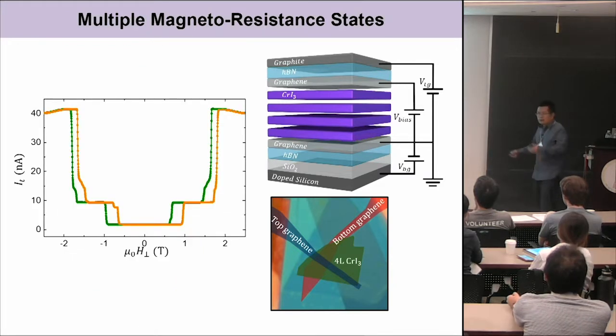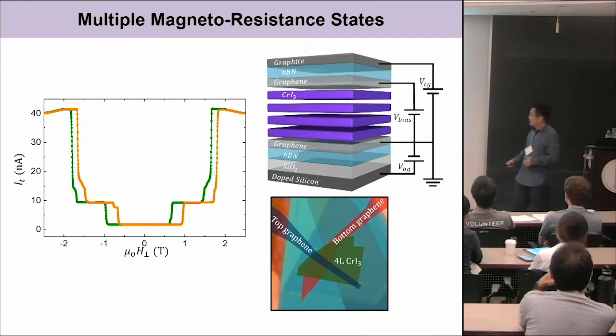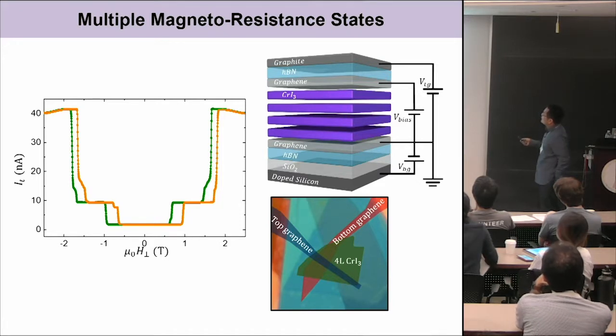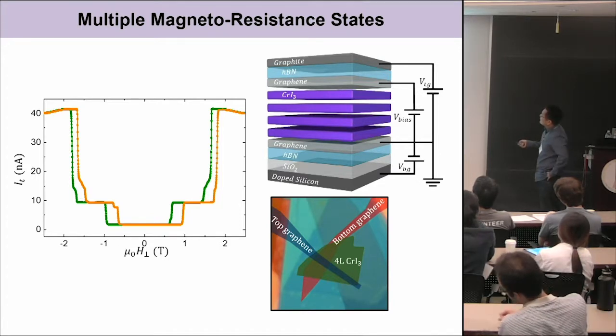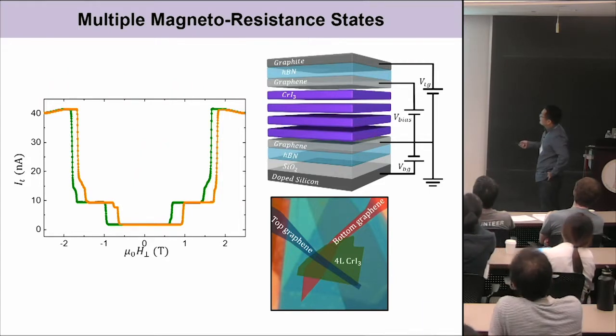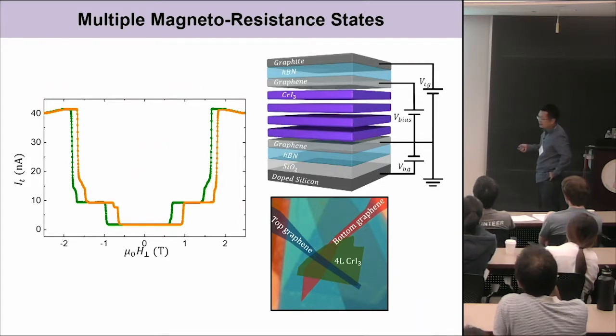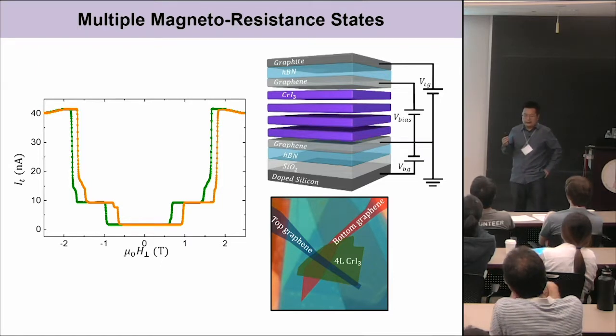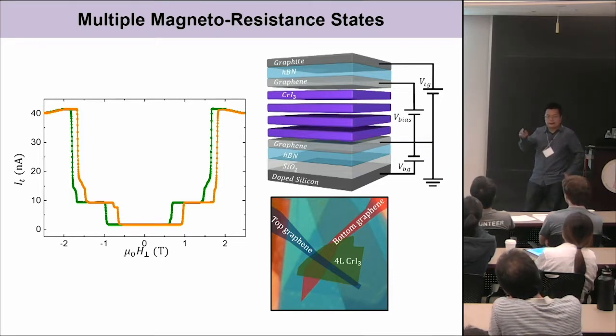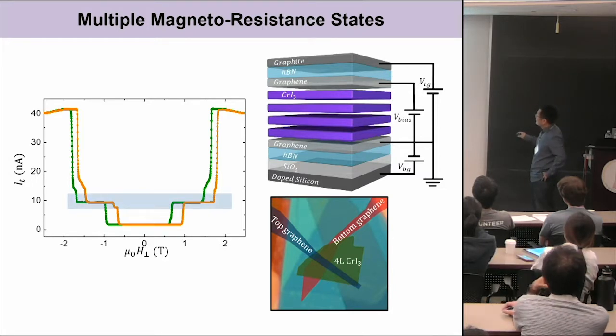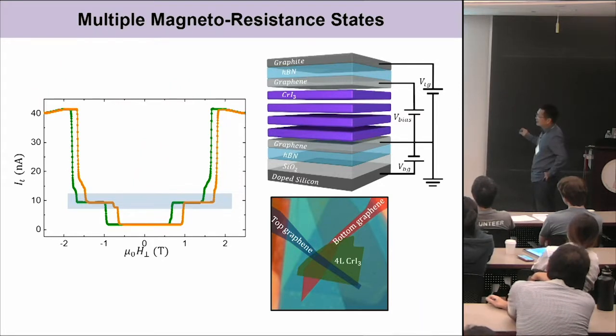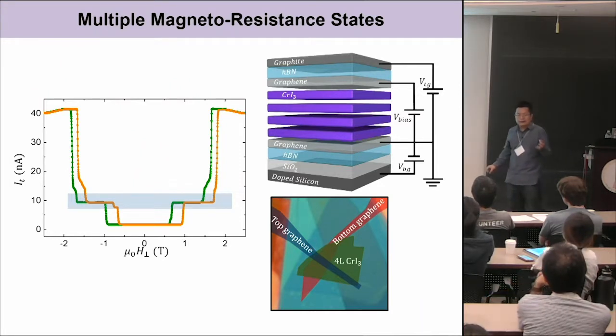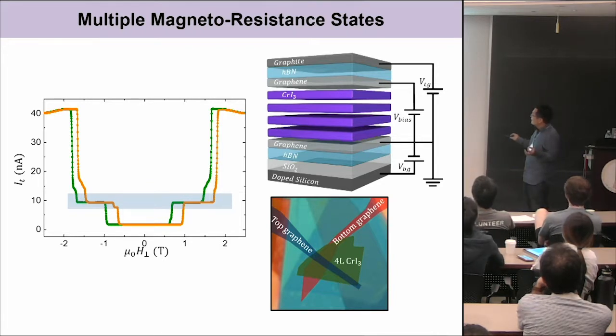And as other groups show, you can keep increasing it, even to a million percent. But what I want to show you here is that in the 4 layer tunneling measurements, a plateau shows up. This intermediate state corresponds to the intermediate magnetization state I showed in the MOKE measurements. This is nice, because if we think about each step corresponding to 1 bit, then there's a potential to realize multi-bit storage.